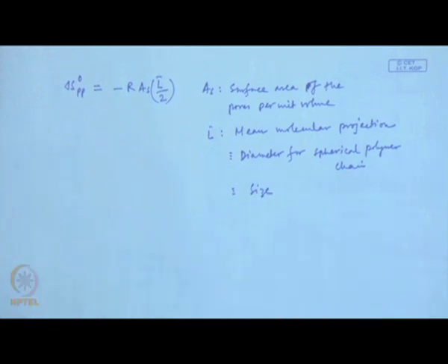Now, as you can think, when a polymer molecule goes inside the pores, the conformational entropy of the polymer chain gets reduced, because the conformations which require the central mass to be very close to the rigid walls of these pores are forbidden.